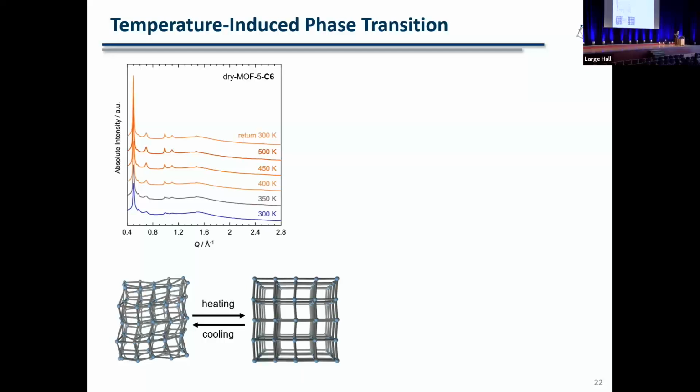So we increase the entropy in the system, but at the same time we increase the order. Doesn't make any sense, right? So what is happening here? When we increase the temperature, we do increase the entropy indeed, and the vibrations of the side chains kick in, and the thing breathes and expands. And at the same time, the zinc atoms, the strong scatterers, go back to their lattice positions, and then we get the Bragg scattering back. So basically, we get Bragg scattering back, but at the same time, we increase the disorder in the system. It's quite an unusual case.